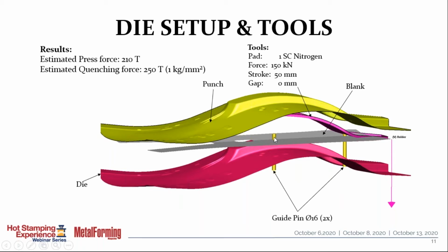Most of the time when you put locators into parts that are being hot stamped, regardless of the type, the material is so soft that it will end up malforming a hole, and you'll put an embossment or a flange onto that hole if the part moves at all during forming. But the pins locate the blank.